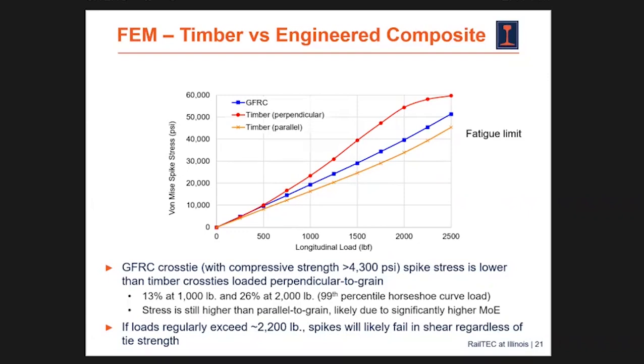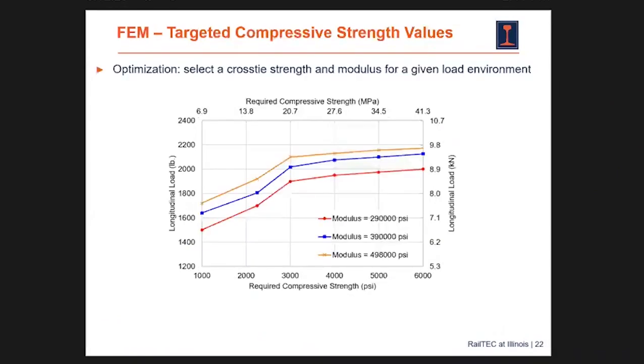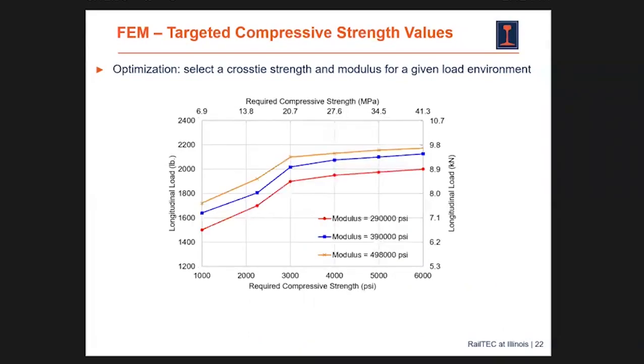being able to come up with a specific compressive strength to target depends on the amount of load that you're going to be applying. This is all basically applying 2,000, or in this case, 2,500 pounds. So we need to optimize, or you could optimize, for a given loading environment. That way you can say, I have these composite ties that don't meet this compressive strength, but I'm still having broken spikes. If you know generally what the longitudinal loads are, perhaps you're a transit agency that has seen these failures, then this could be something to look at, because for a given modulus and a given